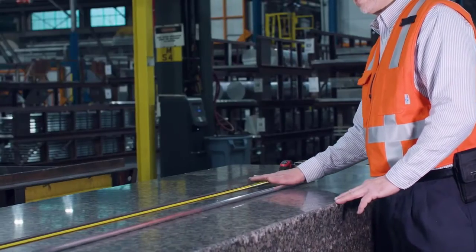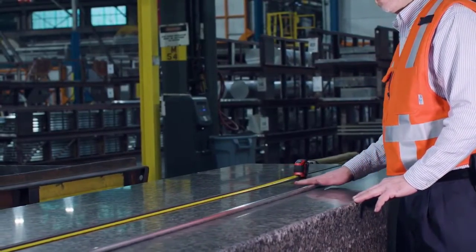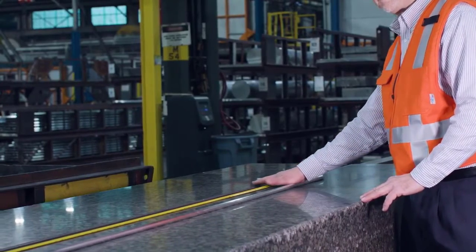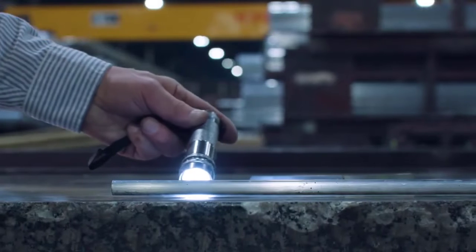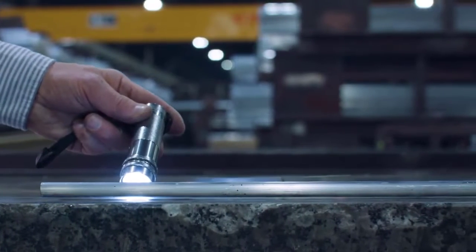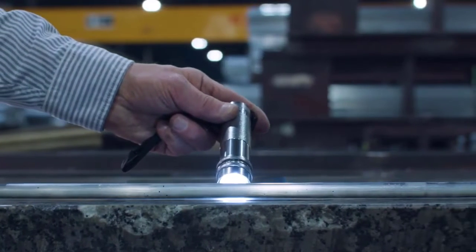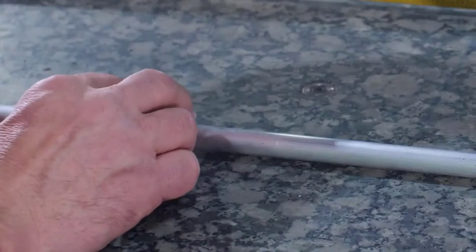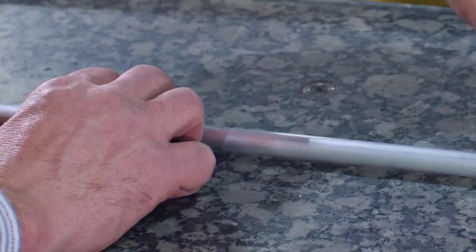We'll first roll the rod to see if it wobbles and help locate the region where the most amount of bow is present. The 0.562 inch rod is oriented on the flat granite table surface, so the largest gap is positioned between the flat surface and the rod. It is also positioned so the weight of the piece minimizes the amount of bow per footnote 3. We will need to support the rod in this case to measure the gap as noted in footnote 9.